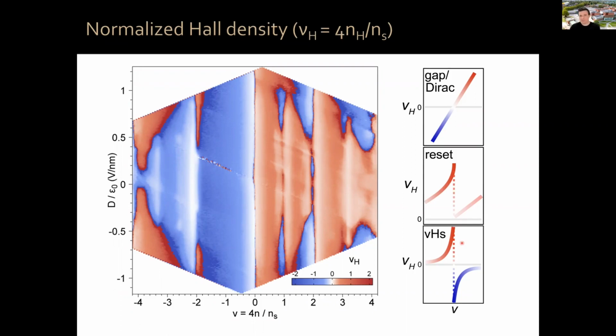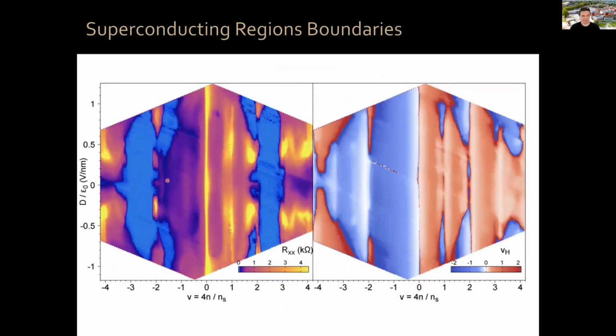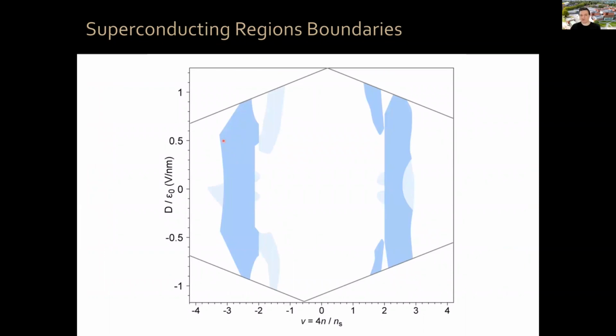So now we can correlate this map with this map and see if any of the features here can be identified or correlated with any feature here. Let's look in particular at the superconducting regions. Just superimposing these two diagrams could be too messy, so let me do this schematically. This is a schematic of all of these regions in this phase diagram, in displacement field and filling factor. These dark blue regions are where superconductivity is present and very robust. These light blue regions are where superconductivity is present but quite weak, and the critical temperature is very small in those regions.